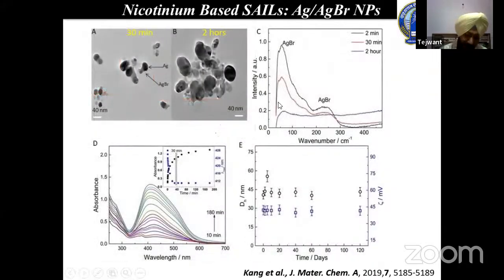Further, many studies have been carried out in this aspect. We have also explored how the shape of the nanoparticles changes as a function of time. In the case of 30 minutes, we can find very nicely placed dense nanoparticles. Once you increase the time, their structure deteriorates because the silver ions are reduced to a much higher extent, and you can see here that much of the area is darker in color.